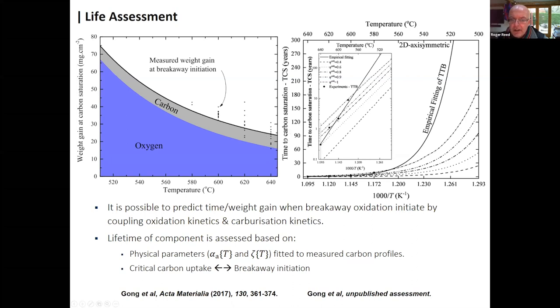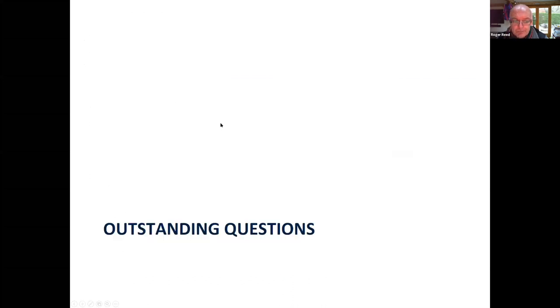And on the right-hand side here, if one plots the time to carbon saturation against inverse temperature, then you can see that an empirical fit to the high temperature data would lead to a line like so, which goes more or less asymptotically to the reactor temperature, about 520 degrees Celsius. But we were able to show actually that those calculations are quite in error, and one needs to do a better job using a more physically based model, using what I described to you in simple terms this afternoon.